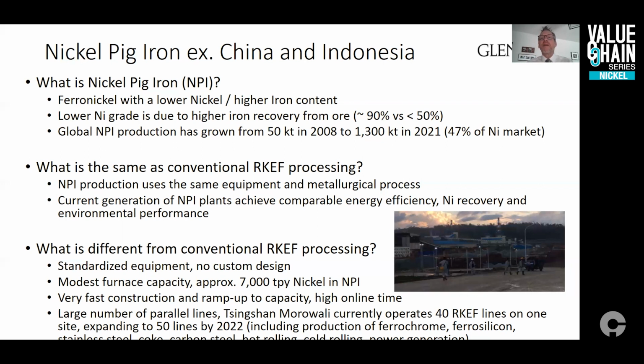Typical nickel production from an NPI furnace is about 25% of that in a modern ferronickel plant. All these things contribute to construction in less than 1 year, ramp up in 2 to 3 months, and high operating online time. Economy of scale is achieved by operating a large number of parallel lines. The Tsingshan Morowali operation in Indonesia presently operates 40 parallel RKEF lines with an additional 10 lines in construction or planned to be in operation by the end of 2022. And this is in addition to the production of ferrochrome, ferrosilicon, stainless steel, coke, carbon steel, hot rolling, cold rolling, and power generation all on the same site. It's extremely impressive.